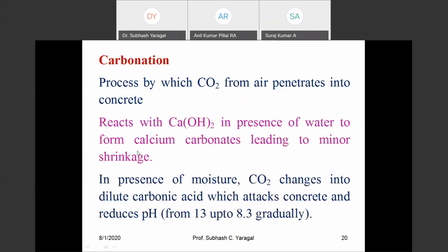Now, what is carbonation? It is the process by which carbon dioxide from the air penetrates into the concrete. It reacts with calcium hydroxide in the presence of water to form calcium carbonate, leading to minor shrinkage. This is one aspect of the problem. In the presence of moisture, CO2 changes into dilute carbonic acid, which attacks concrete and reduces the pH from around 13, an alkaline environment, down to 8.3. We are making the environment acidic, switching from an alkaline environment towards the acidic range.